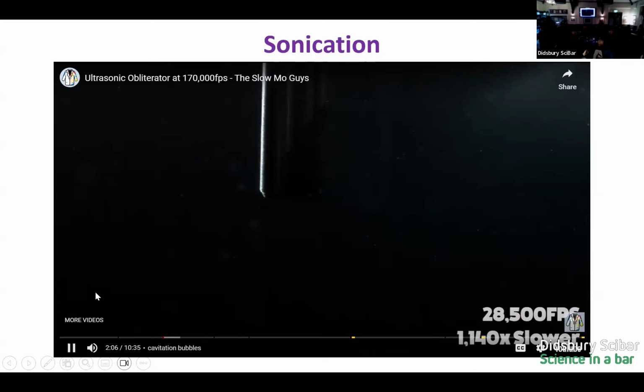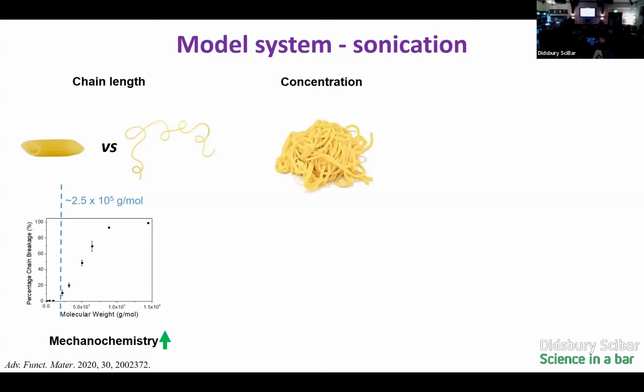So when we look at sonication in our system, we see a number of things. We see a dependence on chain length, as we kind of expected. It gets easier and easier to break our polymer chains as they get longer and longer. We see an effect of concentration. So as we increase the amount of polymer in the material, it gets harder to pull the polymers apart. If we have a really concentrated solution, it's kind of hard to separate these out and pull them and get enough tension across the material to activate them.